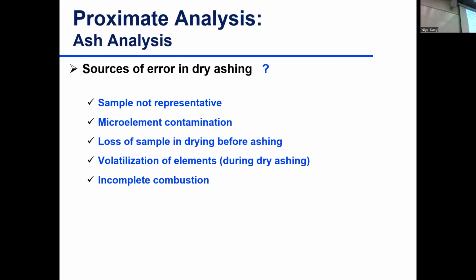So the first thing is that you are getting small amount of your sample. If you don't do a good sampling or sample preparation, your sample cannot be representative of the whole population of your sample. So it's the first step that we need to make sure our sample is homogeneous and representative of the whole sample population. And that might be a source of error. The other thing is that if we don't use an appropriate crucible, there is a possibility of contamination to different elements. Or if we don't pay attention to contaminations, there is a possibility of different contaminations. And then, as you said, loss of our sample because of volatilization of some elements and incomplete ashing or combustion.